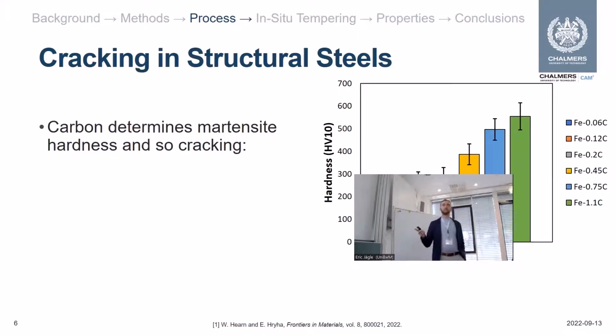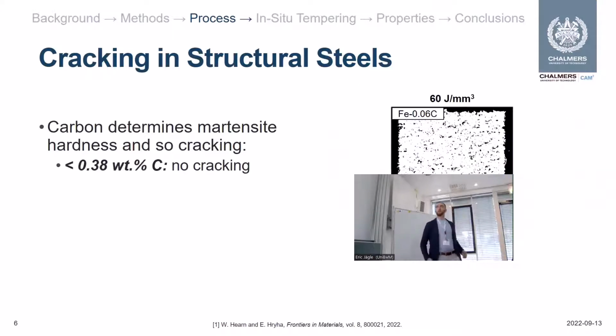Now, in terms of the processing parameters, they also had an impact, but their impact was dependent upon the alloy composition you're looking at. So when you had specimens with relatively low amounts of carbon, below 0.38 weight percent, regardless of the energy input or build plate preheating temperature we used, we don't see cracks. And this is just because at this composition, your material is ductile enough to accommodate any residual stresses and avoid these cracking issues.